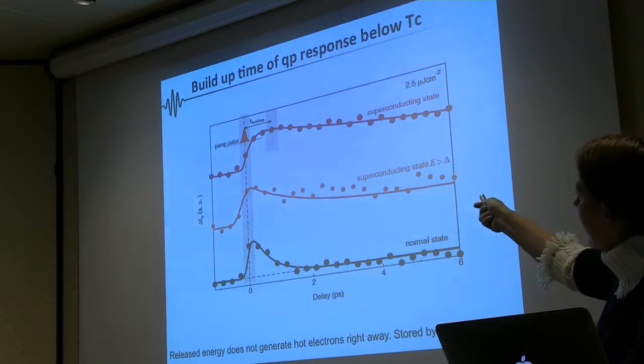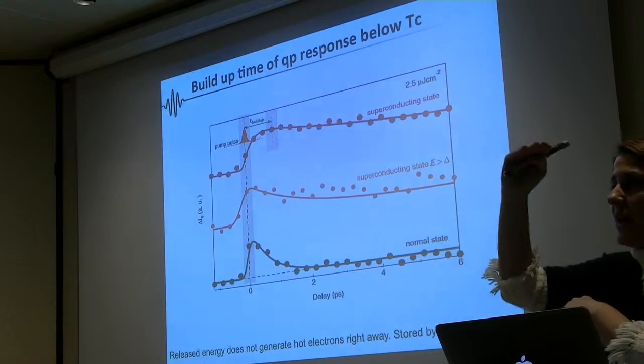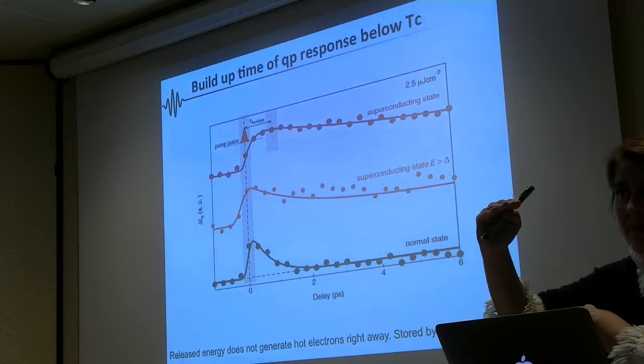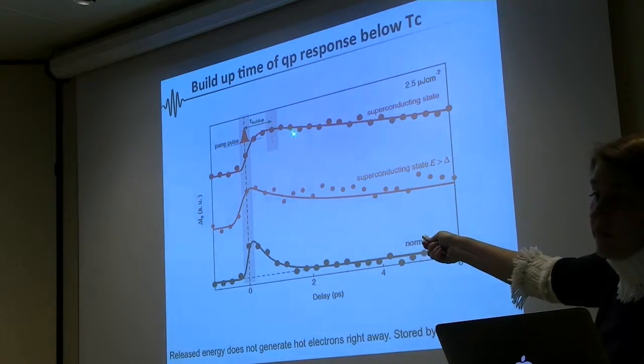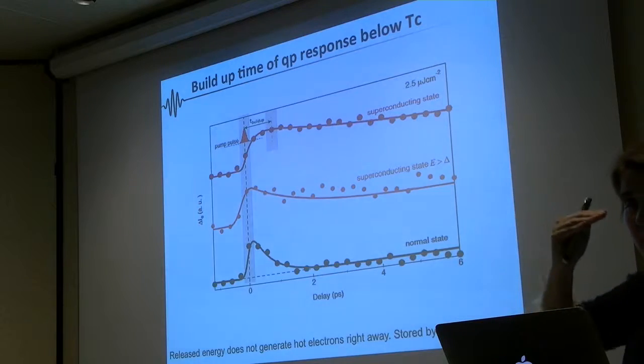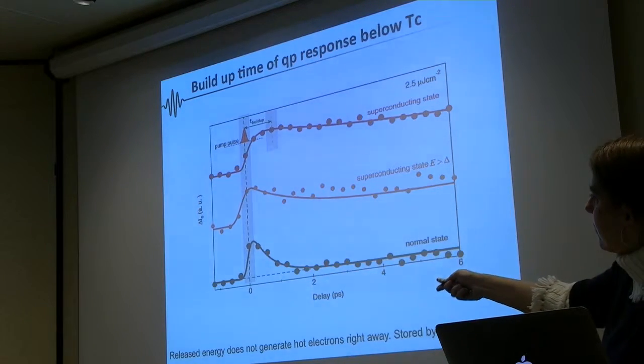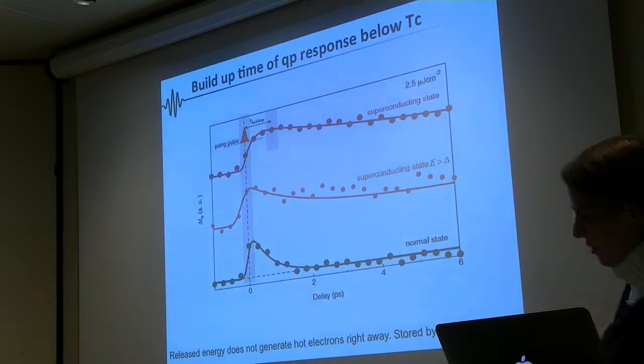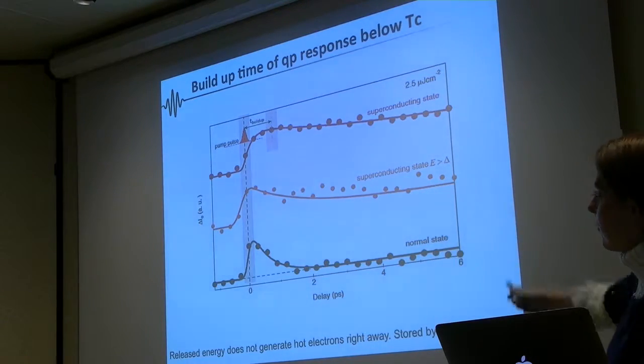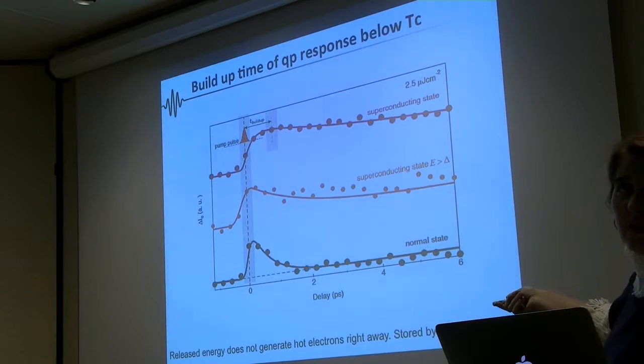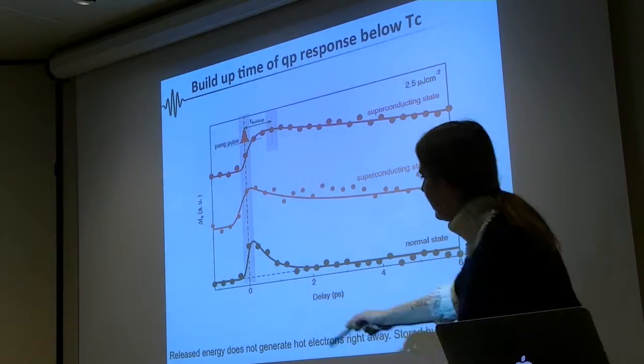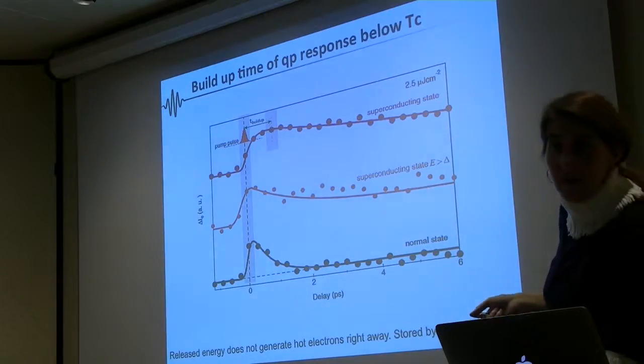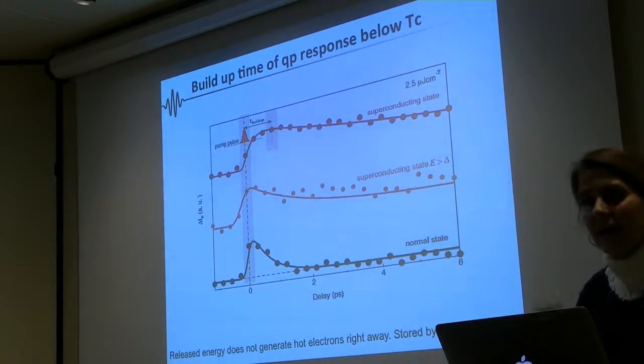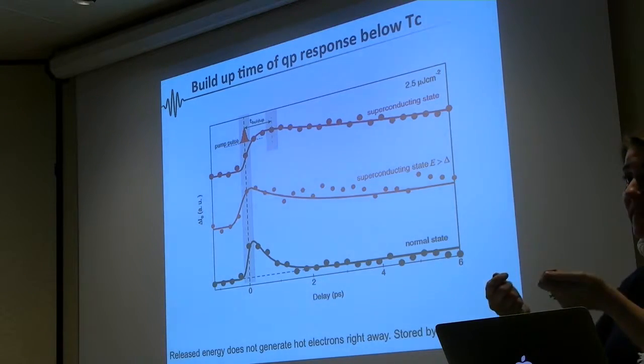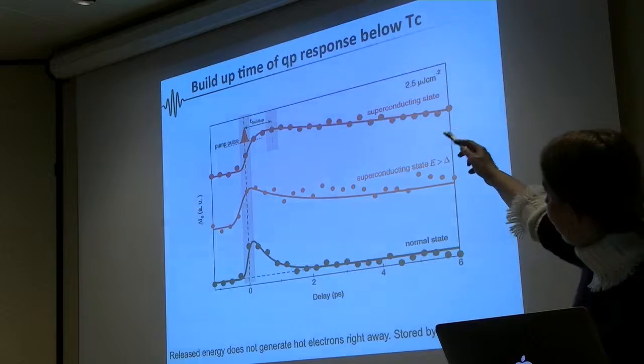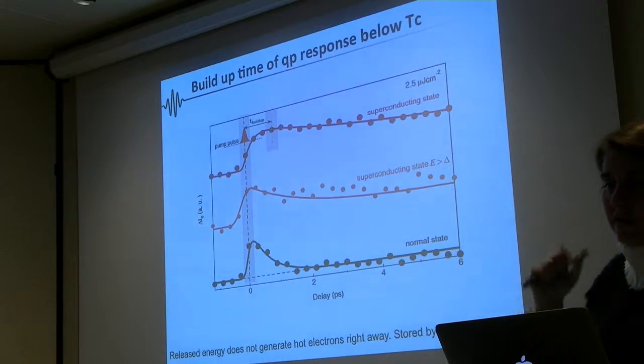So I can really have this selectivity in energy and selectivity in momentum. So you see that if I am in what I call the superconducting state, meaning I'm sampling energy inside the superconducting gap, then there is a delay in the response. But if I measure an energy that is past the superconducting gap, then the response is almost immediate. You see that the peak goes closer to 0. And then finally, if I do the same experiment in the normal state, then you see that the response is also quite fast. So you have a maximum right away, which is what, thinking about a simple picture, you would expect. Come in, excite the system, boom, response is immediate. So there is something particular about the superconducting state, in particular when you are inside the gap.